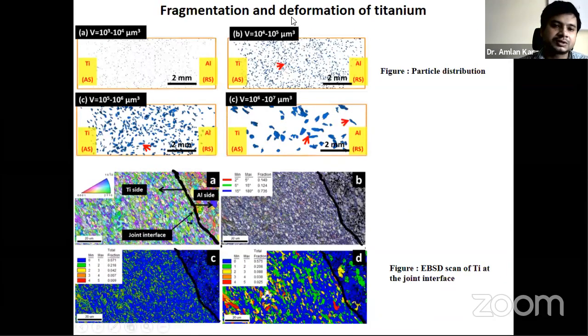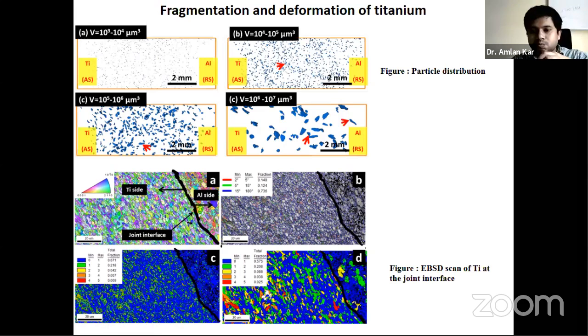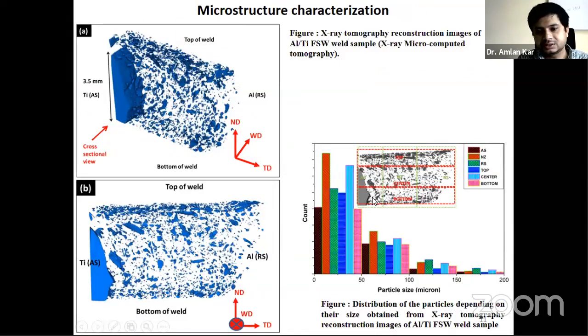Then we have separated out the particles based on their volume or particle size, and we have seen that very fine particles are more or less homogeneously distributed compared to the coarse particles. You can see there is a lot of white, and their distribution and orientation is not very homogeneous. But you can see here the fine particles have very good distributions. Okay, so this is one thing, and this is the other.